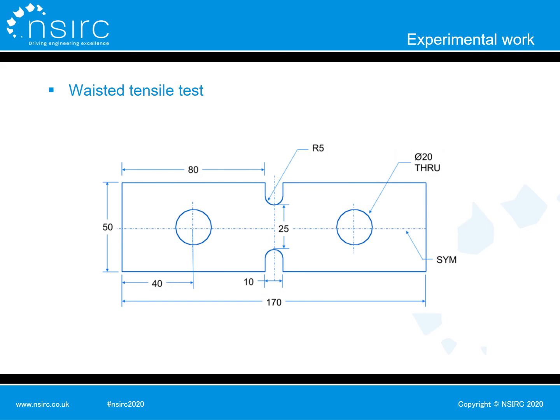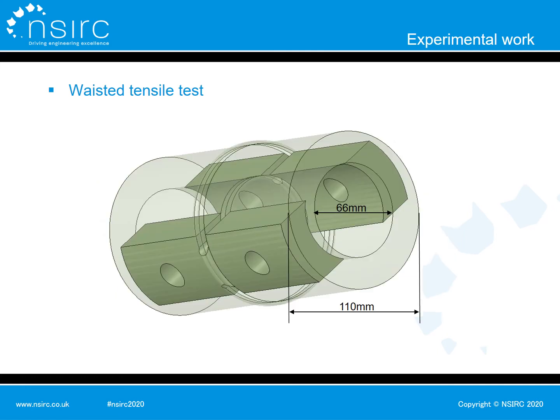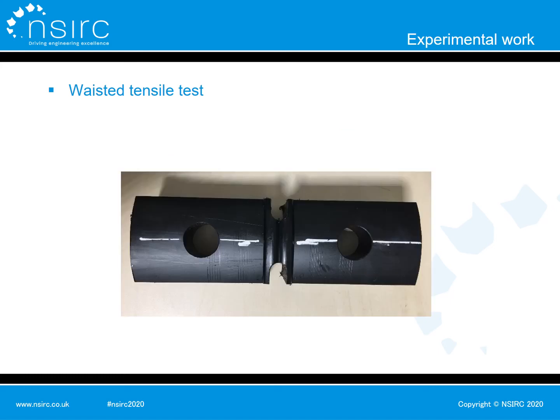Here is the geometry of a waisted tensile test specimen with the length of 170 mm, width of 50 mm, and a reduced waist in the middle. 2 specimens were extracted from one joint opposite to each other. Here is an example of a waisted tensile test specimen.